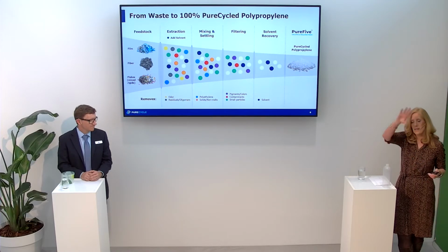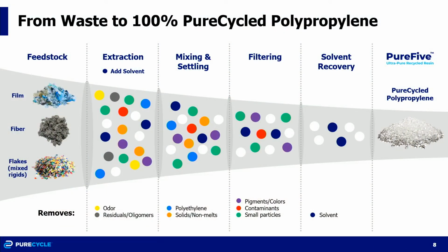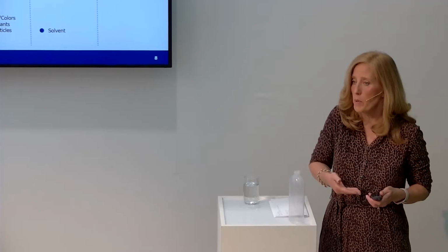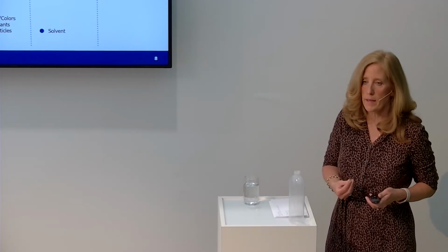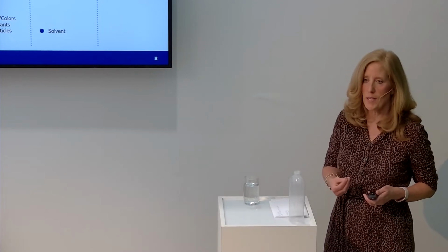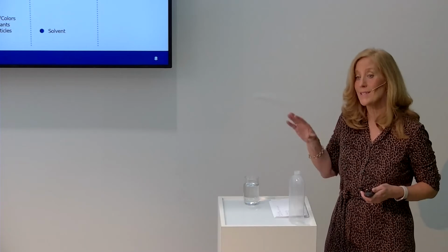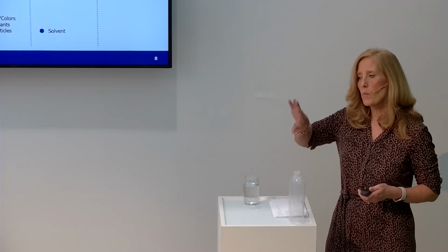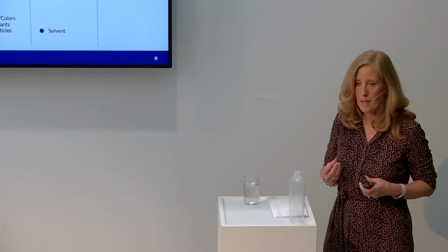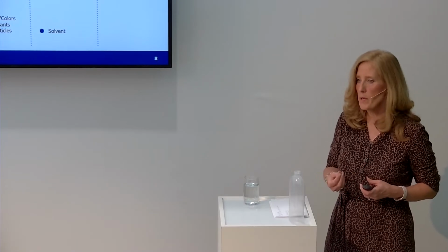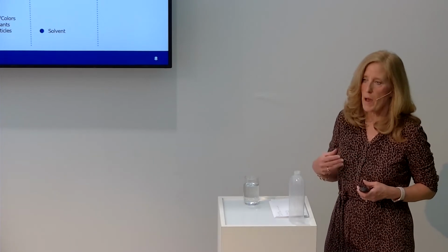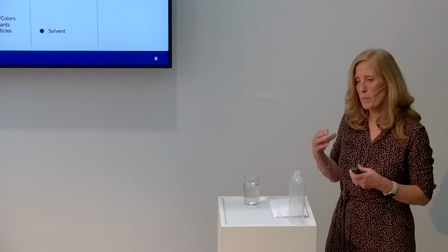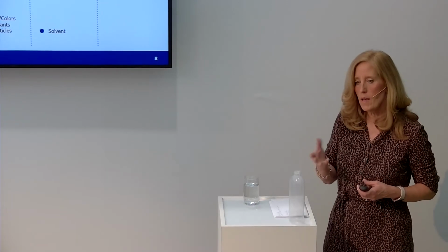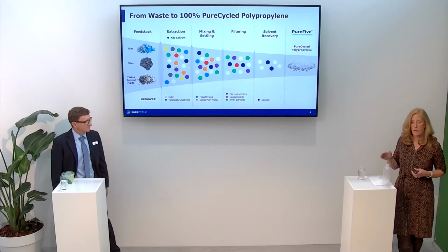And then we go through a mixing and settling tank where we remove the polyethylene component. So for example, if you compound polypropylene, you're a compounder, and you compound polyethylene into the polypropylene, we're going to remove that polyethylene. If you compound calcium carbonate or talc or any kind of filler, we're going to remove that in the settling tank. And then we go through one more process where we take out the dyes. So if we were recycling, let's say, BOPP film, the dyes are most likely going to come out in the third process. And then we come out with a perfectly clear polypropylene, as you can see. But then we also recycle the solvent over and over again.